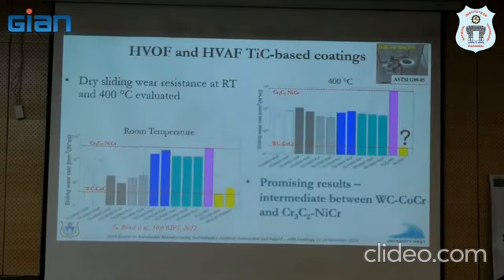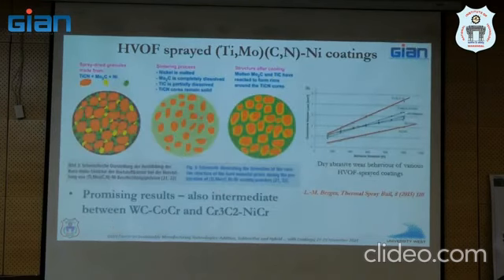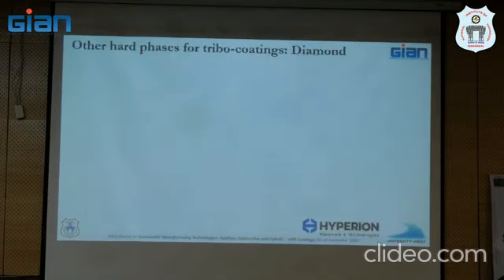So we have looked at titanium carbide by a couple of prominent techniques here, and we always get a performance which is kind of halfway between the two popular materials that I showed for wear, tungsten carbide and chrome carbide. It's somewhere in between. There are a lot of results out there which consistently show the same outcome. Titanium carbide is very nice and gives you something in between those two.